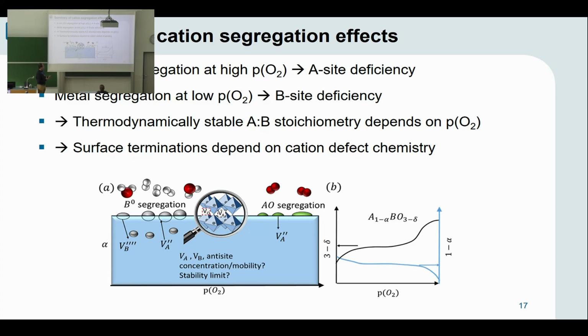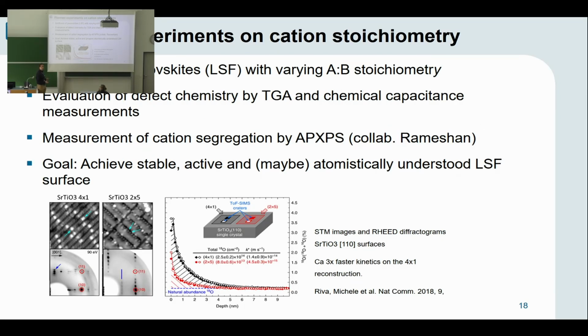And there should be some thermodynamically stable A to B stoichiometry for each material, partial pressure, and temperature. And we want to explore this more in the future. So a quick glance at the planned experiments. Due to the always observed segregation phenomena and the need to have stable, highly active surfaces of perovskites for catalytic and SOFC applications, we want to investigate the effect of A to B non-stoichiometry on the surface stability of LSF in various oxidizing and reducing conditions. And we will do this first by